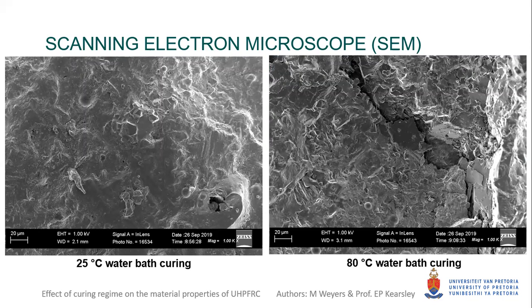Scanning electron microscope images from concrete samples are shown. The images were taken after 90 days of curing, and the scale for both images was 20 micrometers. Both images show the dense microstructure of ultra-high-performance fiber-reinforced concrete.